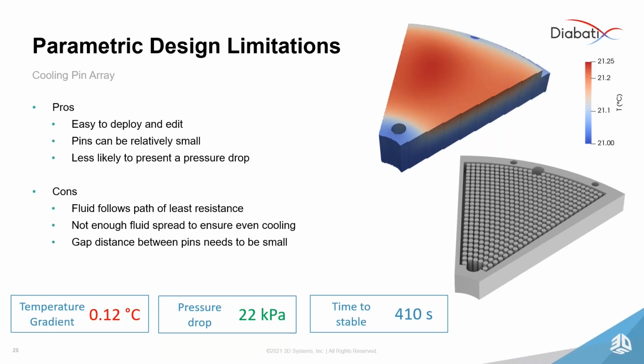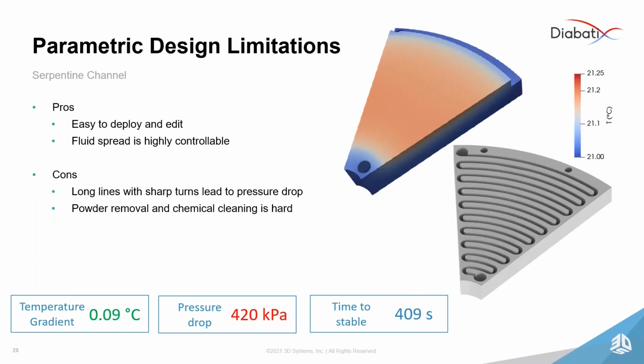Now, that's not the only design that we created. One of the other typical designs that you see coming with this way of designing is serpentine channels. So we designed one as well. We optimized it with parametric optimization, and you see that from a thermal gradient point of view, this design is behaving very well at 0.09 degrees Celsius, but the pressure drop was way too high. We ended up with 420 kilopascal. Again, the limit was 70 kilopascal, meaning your system cannot handle this. So it's useless in the end. Although time to stable was 409 seconds, which is a little bit better than the previous design, it's useless. The pressure drop is way too high. That's only evaluated from a thermal perspective.